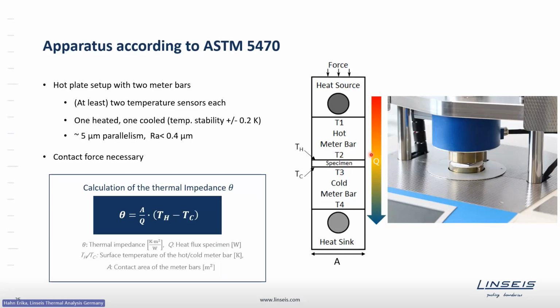When reaching this point, we use this heat flow to calculate the so-called thermal impedance, denoted here with theta, using the sample area, which is the same as the meter bar area, the heat flow, and the temperature gradient over the sample. This property we use then for the further evaluation, which we see in a slide later on. The thermal impedance is the sum of the thermal resistances from the top to the bottom, so including also the contact resistance between the sample and the meter bar.